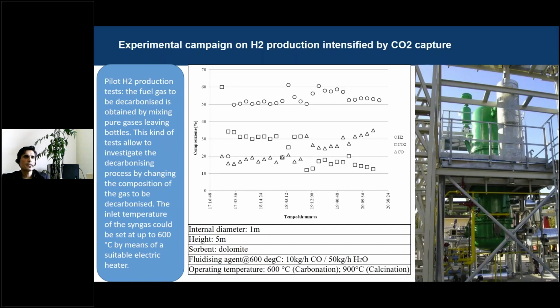Particularly here you can see the composition of the gas leaving the carbonator. We have simulated inside this carbonator, which is a bubbling fluidized bed, 5 meters high with an inner diameter of 1 meter. In this experimental campaign, we fluidized 200 kilos of dolomite with a gas mixture composed of 10 kilograms per hour of CO and 50 kilograms per hour of H2O in order to simulate the water gas shift intensified with the capturing of CO2.